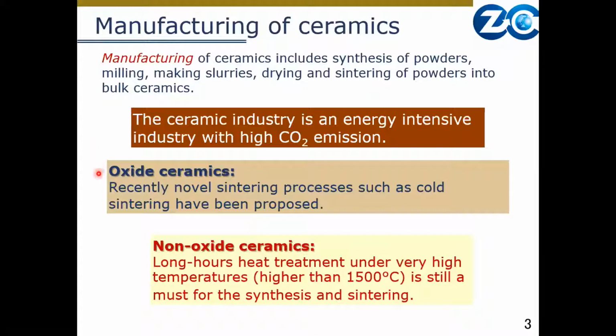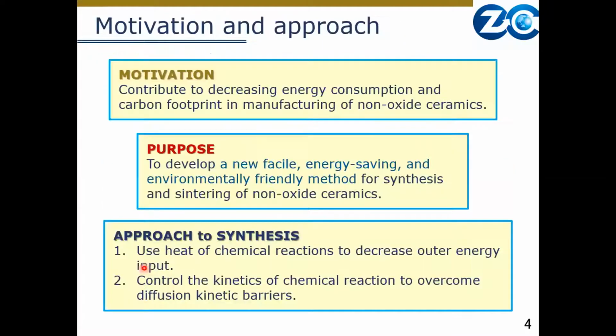In case of oxide ceramics, recently novel sintering processes such as cold sintering have been proposed to decrease temperature of processing and decrease energy consumption. However, in case of non-oxide ceramics, in many cases, long hours of heat treatment under very high temperatures, higher than 1500 degrees C, is still a must for the synthesis and sintering.